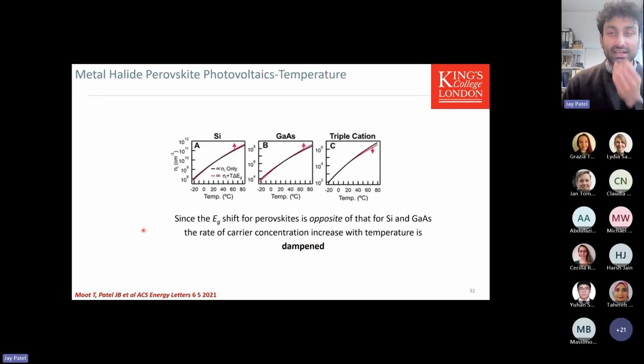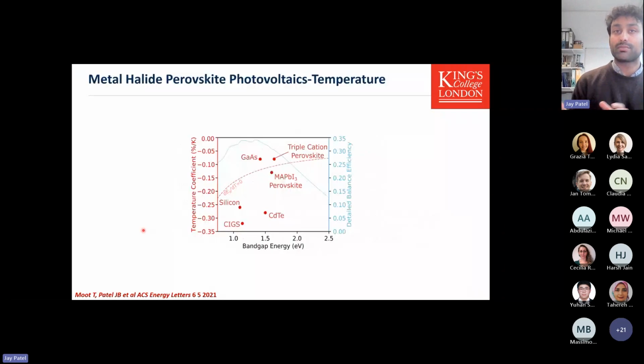What we found is that the implication of this in the device is that the intrinsic carrier concentration, which always increases as you increase the temperature, will actually be dampened for perovskites. So this is great news. It means there'll be less of a temperature effect, less of a change in performance as you change the temperature. We took these measurements, made devices and looked at the devices, and it all matched up pretty well.